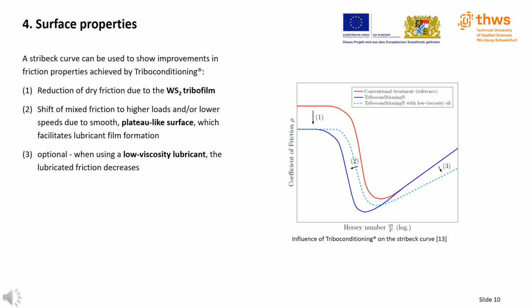At low Hersey numbers in the dry friction regime, the solid lubricant tungsten disulfide reduces friction, C1. Furthermore, the range of mixed friction is shifted to the left towards higher loads and/or lower speeds, C2. This is due to the plateau-like surface that facilitates lubricant film formation. Optionally, triboconditioning allows the use of a low viscosity lubricant. Although this shifts the range of mixed friction somewhat to the right, the lubricated friction, that is the friction at higher Hersey numbers, decreases, C3.